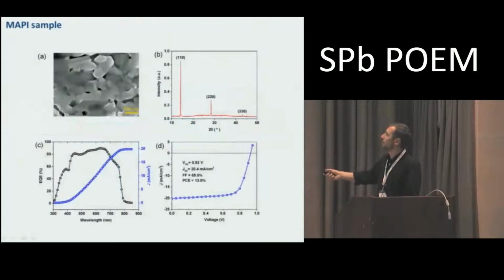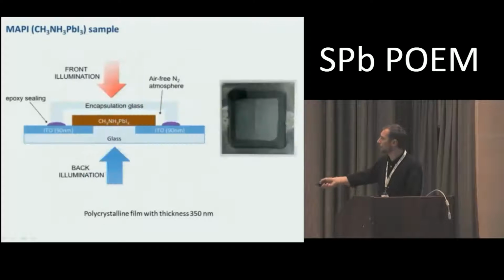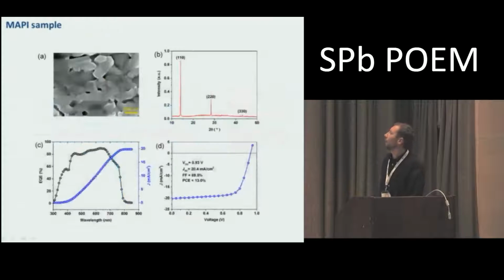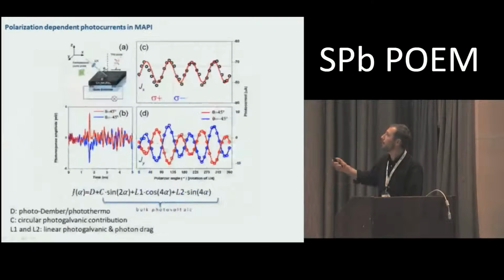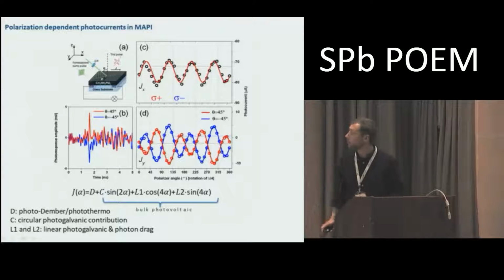So here are some typical characteristics of this material. It is a polycrystalline film with 350 nanometer thickness. The efficiencies obtained with this particular material in a solar cell are not very good, but let's say they are okay. It's about 13%. It's less than the record ones, which are about 20%, but still they are okay.